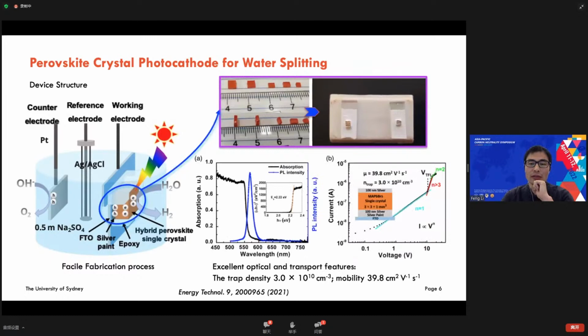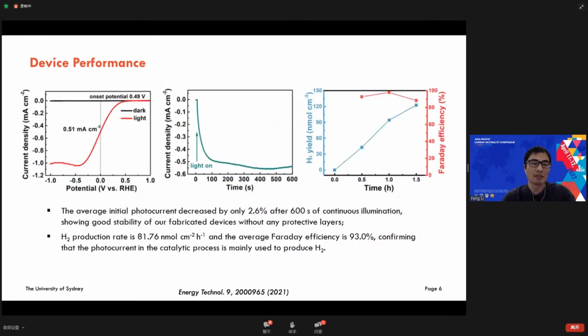Before we fabricate this device, we also checked the optical and electrical properties of this kind of material. We found that the mobility is much higher compared to polycrystals, and the trap density is also quite low. That means the single crystal is not bad from our lab, and we try to use silver paint to contact this one on the FTO conductive substrate, and then fabricate this kind of device.